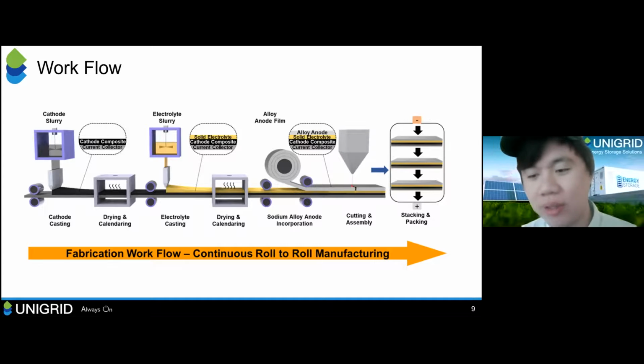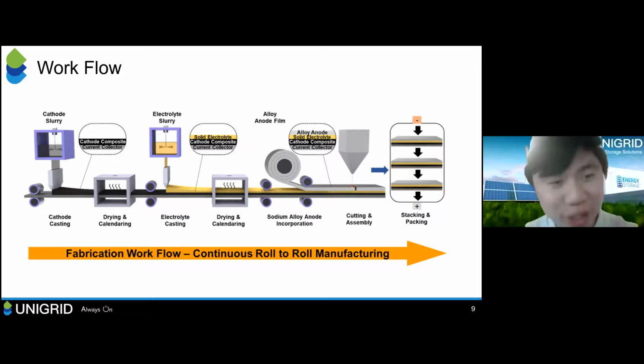But the concern with battery management system in solid-state battery is that it becomes less sophisticated on the thermal management, but a lot more sophisticated on the pressure management. Because solid-state materials are made of solid particles coming in contact, we always have to ensure that they have good conformal contact with each other. It's not like liquid that will flow and wet all surfaces. So when we operate the cell, it has to be under a certain amount of either uniaxial or isostatic stack pressure, and that pressure has to remain constant within its operation range. And here we are talking about megapascals. This is about 100 times higher than the pressure we apply in lithium-ion batteries.